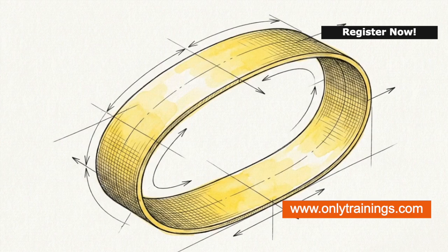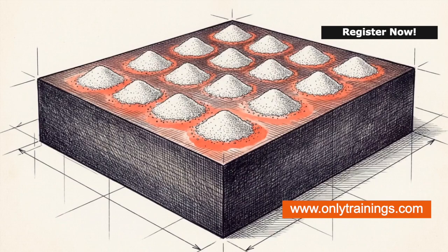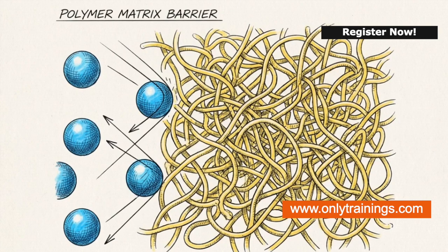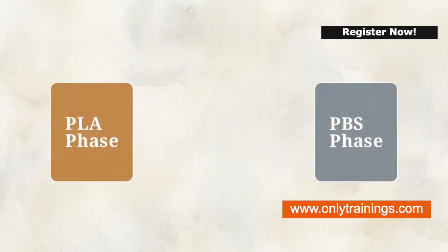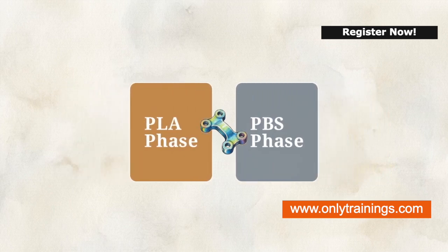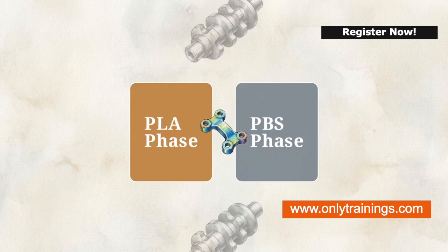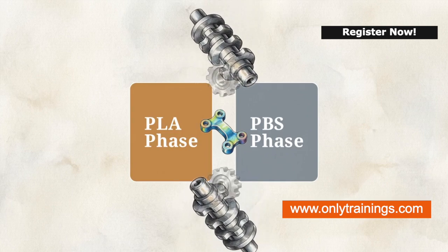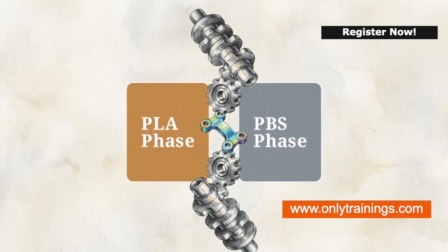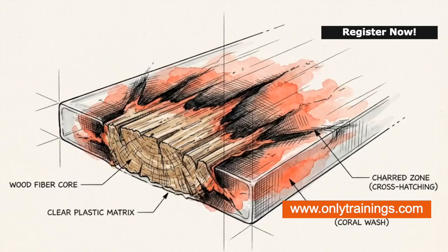They are highly valued for their fast crystallization kinetics and flexibility. However, the standard nucleating agents that industry relies on for polyolefins fail completely when introduced into the complex matrices of these biopolymers. Formulators use engineered compatibilizers. This diagram shows a targeted chemical compatibilizer acting as a bridge, locking an incompatible PLA phase with a PBS phase. But screw configuration dictates whether that bridge survives. Aggressive kneading blocks generate high shear that physically fractures the compatibilizer. The chemistry becomes even more fragile when adding natural fiber reinforcements, which often trigger antagonistic reactions with the compound's stabilizing additives. A highly advanced chemical additive package is useless if the mechanical shear profile tears its functional chemistry apart before the plastic reaches the pelletizer.